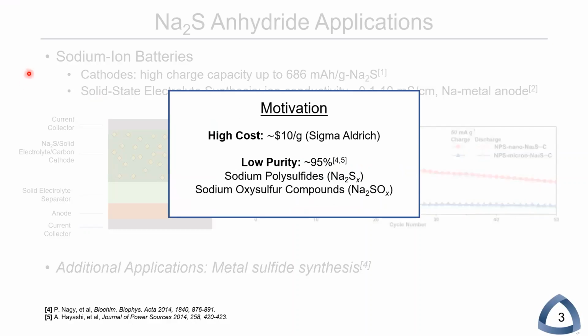However, anhydrous sodium sulfide is currently fairly expensive, on the order of $10 per gram from Sigma-Aldrich, and has relatively low purity around 95%, with the primary impurities consisting of sodium polysulfides, as well as sodium oxysulfur compounds such as sodium sulfate and sodium sulfite.